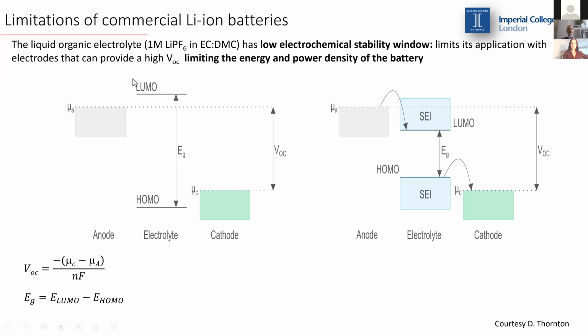In a stable electrolyte, the LUMO of the electrolyte and the HOMO of the electrolyte have to be above and below the electrochemical potential of the anode and the cathode respectively. If this is not the case, like in this figure here, if the electrochemical potential of the anode is above the LUMO of the electrolyte, this can be easily reduced by the anode, and therefore it can lead to a degradation of the electrolyte or the formation of a solid electrolyte interface, typically called an SEI layer.